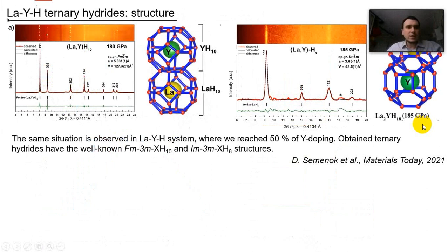We also investigated the structure using synchrotron sources. We investigated the crystal structure of these hydrides, and we found that the crystal structure is pretty simple. Actually, it's just a cubic sublattice of metal, where the lanthanum and yttrium are randomly mixed. So there is no order, and the lanthanum and yttrium can replace any position in this crystal. And we also have a very high symmetry cubic sublattice of hydrogen. It's an atomic sublattice, which is exactly responsible for the high temperature superconducting properties of those materials.